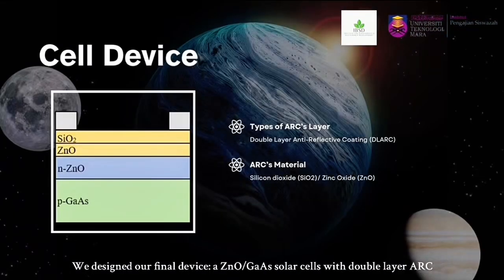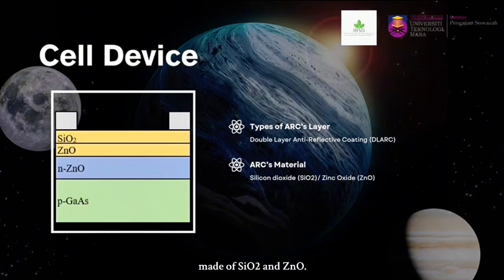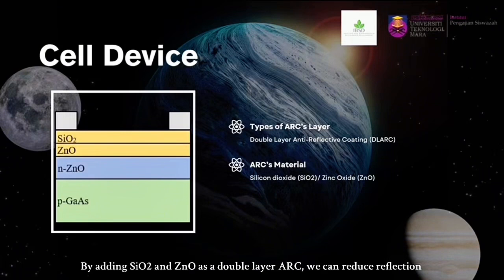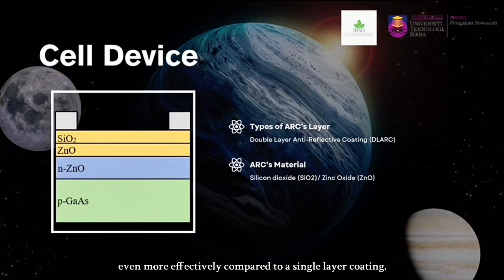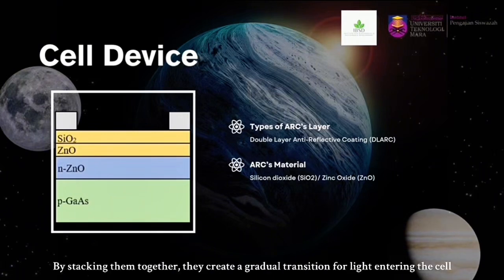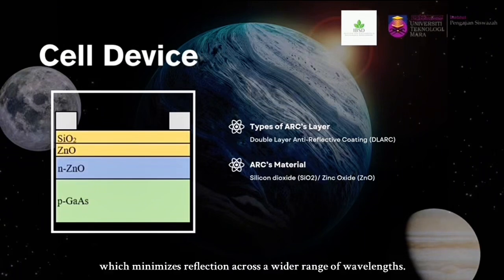We designed our final device, a zinc oxide gallium arsenide solar cell with a double-layer ARC made of silicon dioxide and zinc oxide. By adding silicon dioxide and zinc oxide as a double-layer ARC, we can reduce reflection even more effectively compared to a single-layer coating. Silicon dioxide has a low refractive index, while zinc oxide has a higher refractive index. By stacking them together, they create a gradual transition of light entering the cell, which minimizes reflection across a wider range of wavelengths.